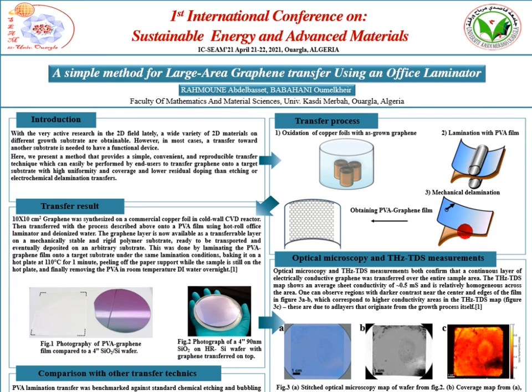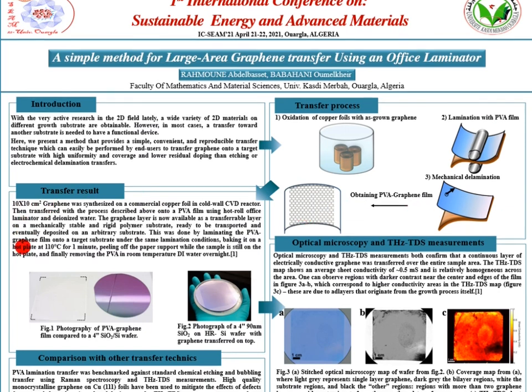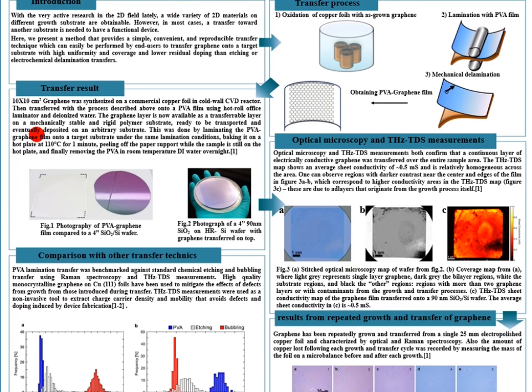The PVA film was then mechanically delaminated from the copper surface, lifting the graphene along with it. The graphene layer is now ready to be transported and eventually deposited on an arbitrary substrate. This was done by laminating the PVA graphene film onto a target substrate under the same lamination conditions and finally removing the PVA in room temperature deionized water overnight.